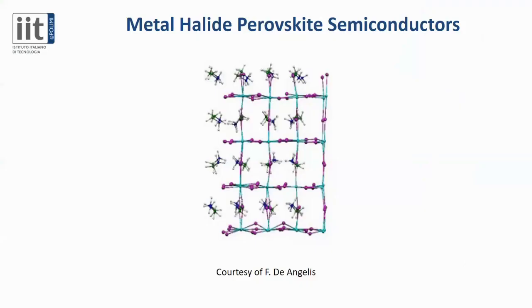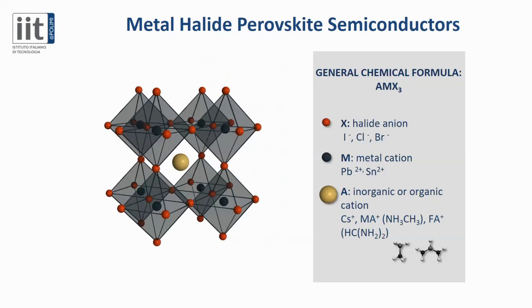We have been hearing about perovskites also in the previous talks. Metal halide perovskite is an ionic solid, which can self-assemble close to room temperature. Thus, the crystal is mainly built on ionic and sometimes hydrogen bonds. The general chemical formula of this type of perovskite, which works as a semiconductor, is AMX, where X is generally a halide anion, M is a metal cation, which can be lead or tin, and A is an inorganic or organic cation. So the first two make the inorganic cage through octahedra, while the A cation is generally in the middle of this cage.